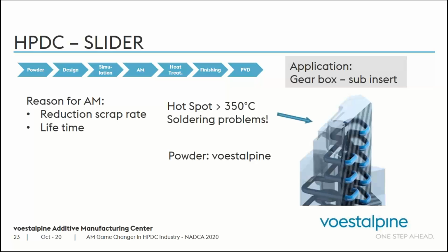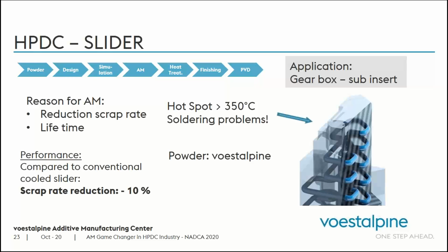Another example is this slider as well. The application here is a gearbox sub-insert. And if you look, the challenge here was there was a hot spot on the traditional insert over 350 degrees C, causing some soldering problems. So in this application, we took a complete approach to provide a solution to our customer, from the powder, design, simulation, additive manufacturing, building the insert, heat treatment, including as well the PVD coating that we have been able to apply. So compared to the conventional cooled slider, the scrap rate was reduced by 10%.